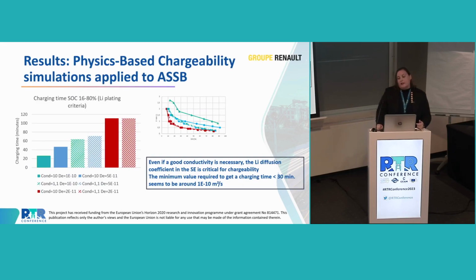From the results coming from the Renault Group, this was another great achievement of the LISA project, because when we are going from the liquid system to the solid system, we all know that conductivity is always an issue, right? But we weren't aware that the lithium diffusion coefficient was something that we needed to really look into. And why is that? If you look at the two graphs, the red one compared to the green one, you will see that the conductivity is almost the same, but the diffusion coefficient of lithium really